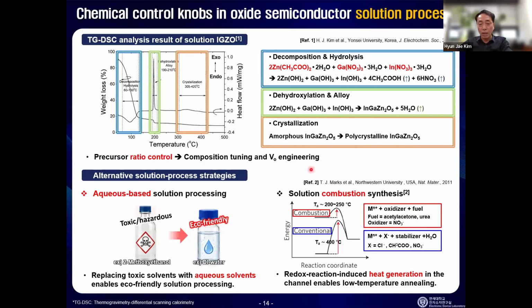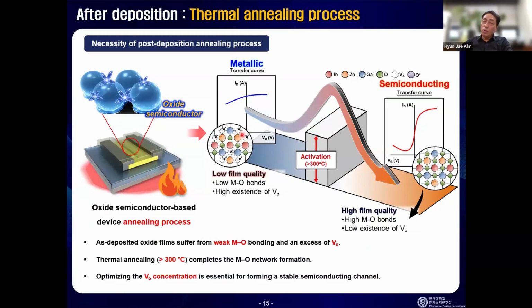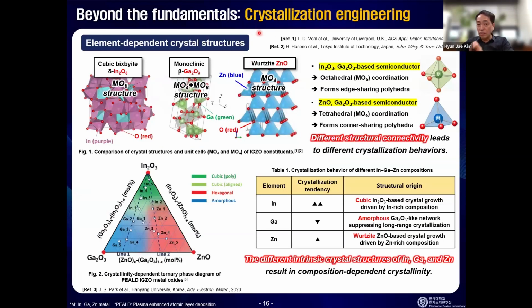Okay, this was hot a long time ago, 10 years ago, 15 years ago, and some people even try to come up with not toluene or carbon-containing solvents. They try to do water, aqueous. And the very famous group at Northwestern, they're famous for solution combustion synthesis for oxide semiconductor. Whatever you do, sputtering or solution-based, you could start with the metal or you could start with the insulator. Whatever you do, you have to anneal at 300, 400. Then the material becomes semiconducting like this. So people call it activation.